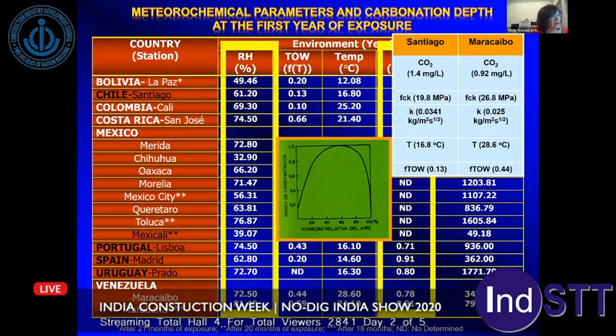As I said before, Maracaibo Station shows the highest temperature and therefore corresponds with the greatest depth of carbonation. High temperature may reduce the moisture inside the concrete, favoring the entry of CO2, in contradiction to what's observed in Mérida, Mexico. Mexico has the highest temperature of Mexican test location. In spite of this fact, it was not the location with the most carbonated concrete in Mexico. This seems to indicate that the average temperature should be higher than 25 degrees C to cause an effect similar to the one observed in Maracaibo.